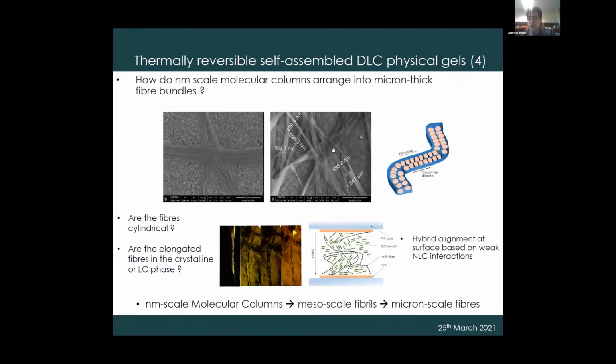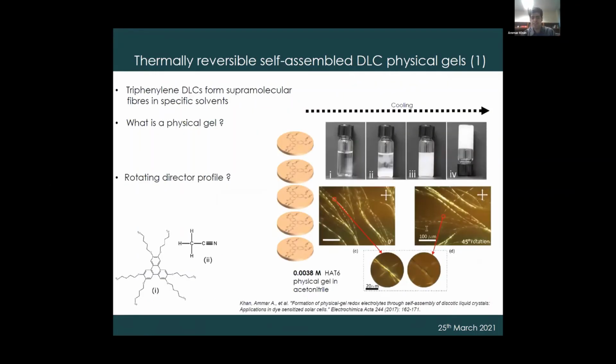And they did not look cylindrical, which was what we initially thought that they looked like. So to our best guess, these molecules are forming these kind of aggregates in a solvent medium, and so you have this elliptical cross section, and what we think is happening is that you have these elliptical fibrils coalescing into these large fiber bundles, which also have some sort of elliptical cross section, and this tends to occasionally rotate, and it gives you different amounts of scattering, which gives you these fringes that you see here.